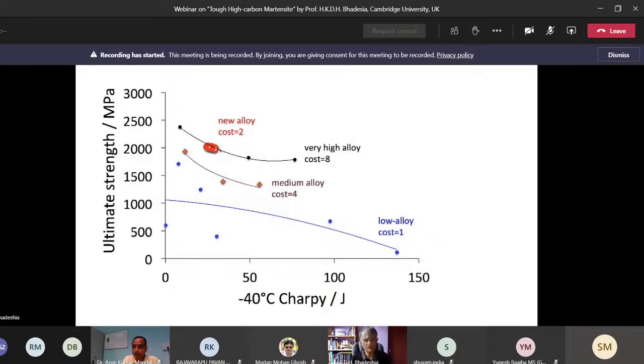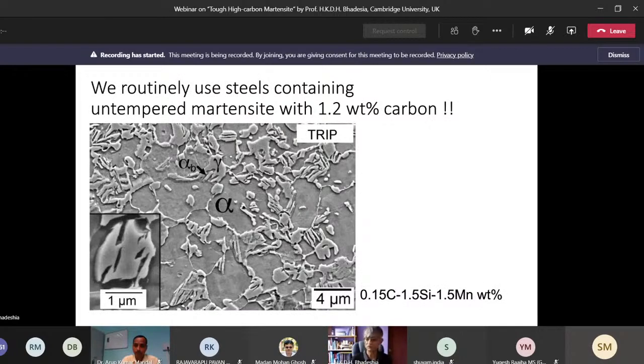I'm going to slightly change the subject because earlier on I said that we have 1.8 weight % carbon, 1.6, 1.4, and we're not going to be able to use it because we have to weld it. But I can tell you that there are already steels in service and in automobiles in which the martensite contains 1.2 weight % carbon without any problems, okay? And this is an example. This is known as a TRIP-assisted steel. TRIP stands for Transformation Induced Plasticity.